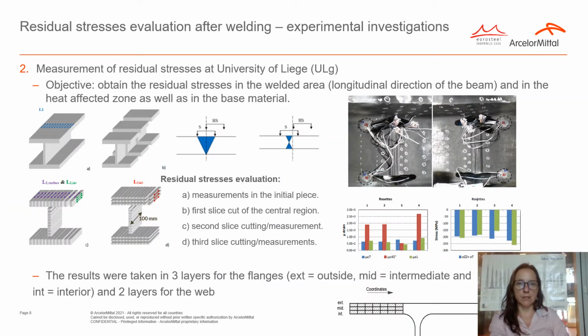The measurement of the residual stresses was performed at University of Liège using the traditional slice method. Measurements were performed in the weld, in the heat-affected zone, and in the base material. The measurements of the lengths are first made on the initial uncut piece, after the other measurements are carried out during the slice cutting. The stresses were calculated for each element based on the total elongation, and finally the distribution of the residual stresses in the section is obtained.